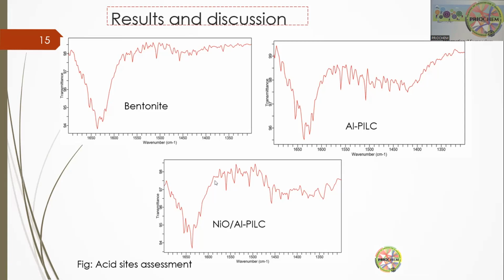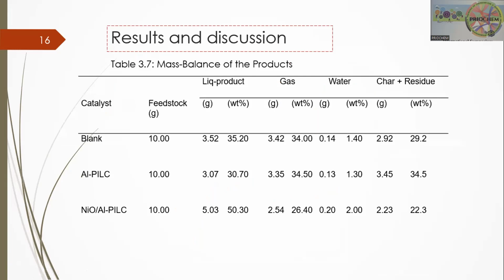But there is an increase in the Lewis acidity, and it is expected when you introduce a metal oxide onto the clay. There should be an increase, and here the absorption bands have increased, suggesting an increase in the Lewis acidity overall. The Bronsted and the Lewis acidic sites are present in all the materials. So here is the result, the mass balance of the products after the reaction.